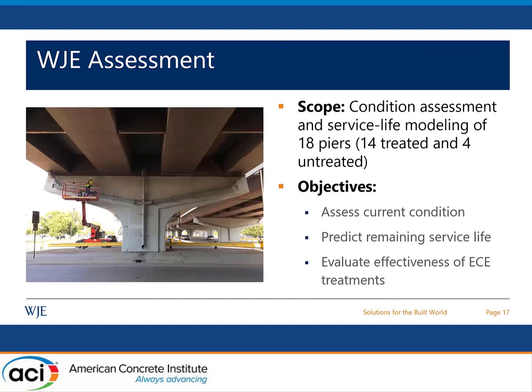WJE went out to these bridge piers in 2018, rather 20 years after the major rehabilitation effort. And our purpose was to perform a condition assessment and service life model of the piers. We looked at specifically 18 of them, 14 which had been treated with ECE and 4 which had not. And our objectives were to assess the current condition of these piers, predict the remaining service life so that we could help inform repair decisions, and then also evaluate the effectiveness of the ECE treatments.